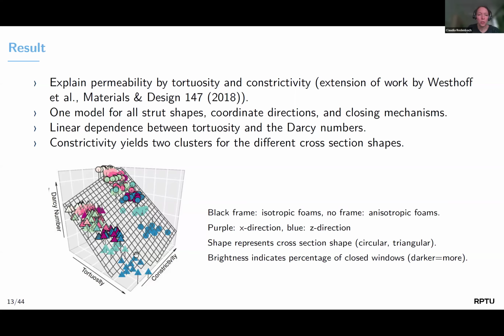So basically what we see is if you stick to the same shape, then the more windows you close, the more the permeability goes down. That's not a surprise. Also, of course, in the anisotropic ones, the direction would then play a role. So if everything is closed in Z direction, the Z permeability goes down. And when it comes to the different shapes, these triangular struts tend to be kind of locally a bit thinner, meaning they extend more into the windows, making the space for the flow to squeeze through smaller. So therefore, this explains the difference here in the constrictivity, and with that also the permeability.